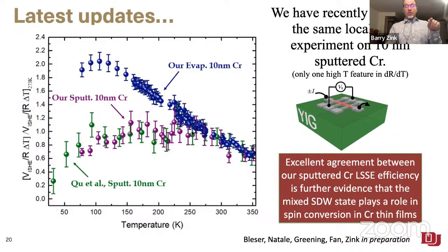One other note, I don't have the data ready, but in the sputtered chromium that we have, we only see one little blip in the DRDT, not these two, and it's at a higher temperature. I don't recall exactly whether it's right at 300 Kelvin, but it's closer to 300 Kelvin. So for whatever reason, at the same thickness in the sputtered case, the strain state is such that you get a single transition into antiferromagnetism that happens at about the expected transition temperature.